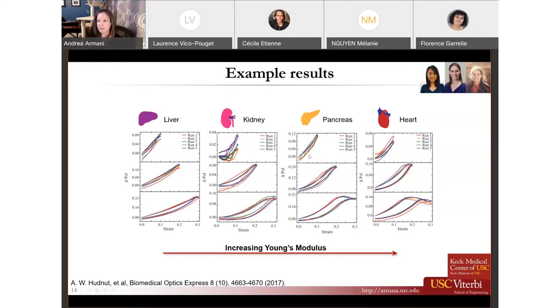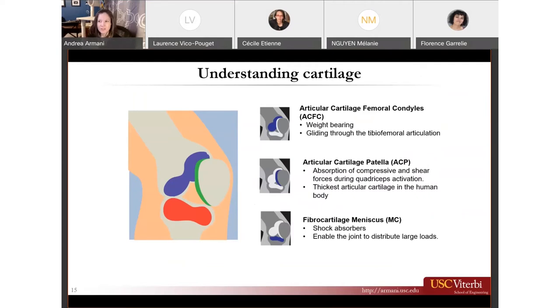One interesting feature of the pancreas and the heart is that as you begin to increase the strain rate, you then see a subsequent decrease. And this is because of the complex internal structure of the pancreas. It's not simply aligned fibers. They actually begin to have a much more complex network, and they do something called buckling, which we were able to model using FEM modeling, which is also an interesting project. So then cartilage.